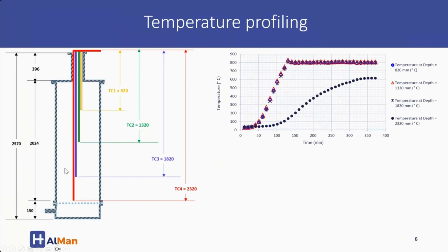For this particular profiling, we had about 100 kg of material filling the retort, which went up to a certain height. So these two thermocouples were not embedded into the material, and there was a significant lag between them and the thermocouple that was embedded in the material.